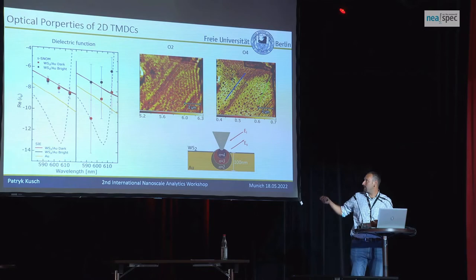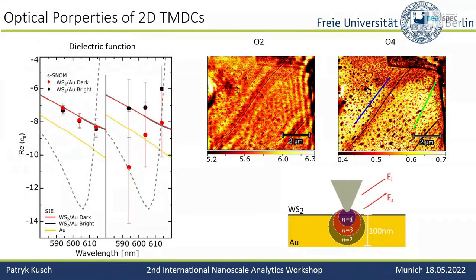In the ellipsometry, at both spots we see exactly the same behavior — of course, ellipsometry probes a large volume of about one micrometer with a large penetration depth, so we see no influence of the tungsten in ellipsometry. In the SNOM second harmonic it was hard to recover the dielectric function of the tungsten. But once we go to the fourth harmonic and use the inversion method, we get negative values that start following the trend of the dielectric function — still shifted due to doping effects, but we are able to do it.